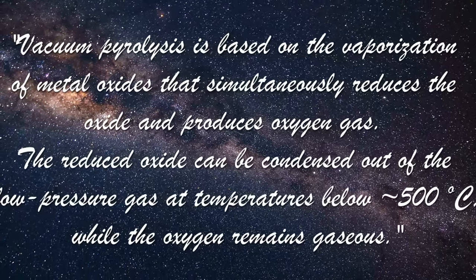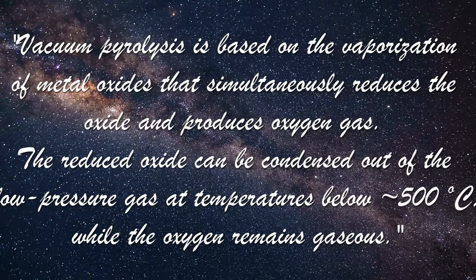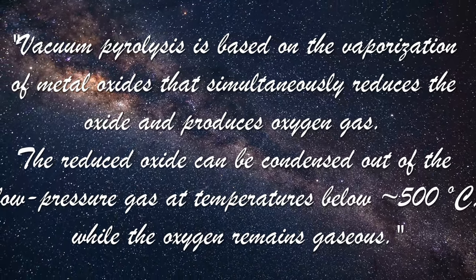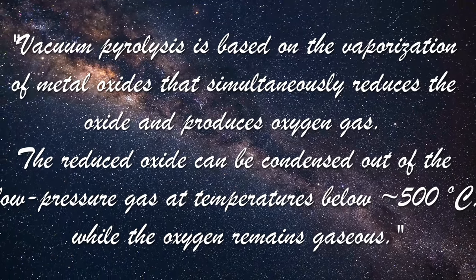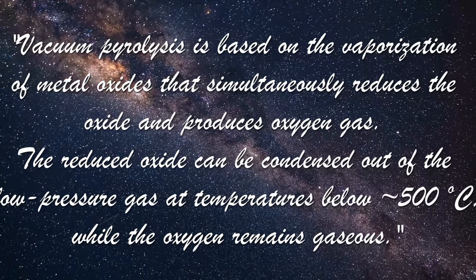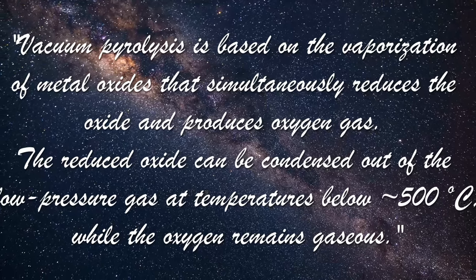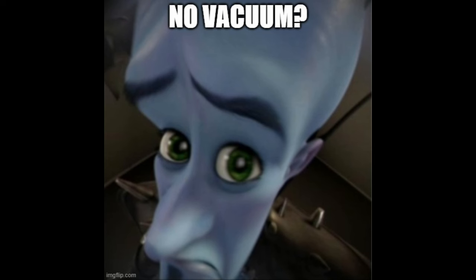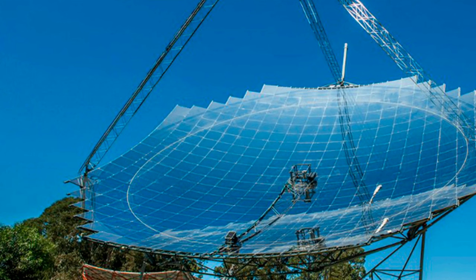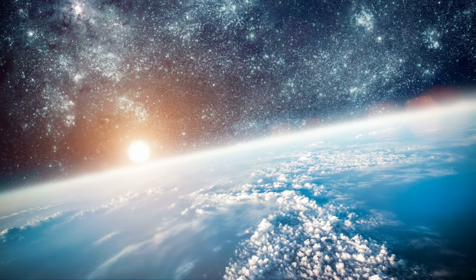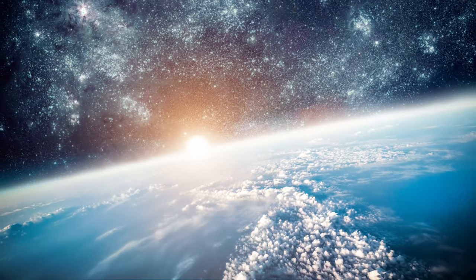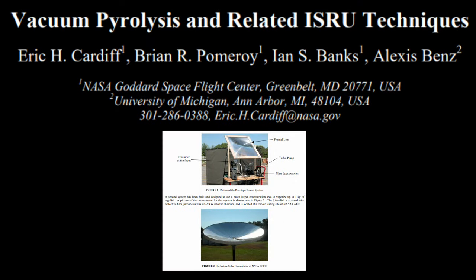Quote, "Vacuum pyrolysis is based on the vaporization of metal oxides that simultaneously reduces the oxide and produces oxygen gas. The reduced oxide can be condensed out of the low-pressure gas at temperatures below 500 degrees Celsius, while the oxygen remains gaseous." No vacuum? No problem. You can compensate with temperature using solar concentrators even on our thick, wet, dripping atmosphere-soaked mud ball of a planet, which is exactly what our pantheon of gods, the authors of this paper, did. But what really induced a sudden and dire need to change my pants was this statement.